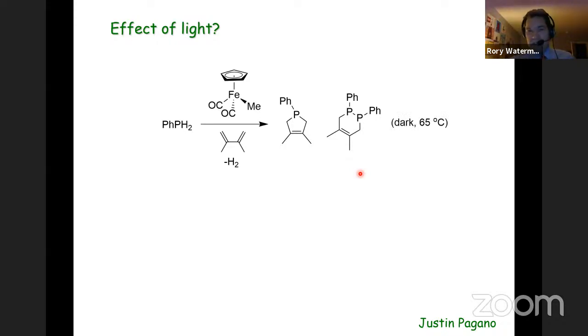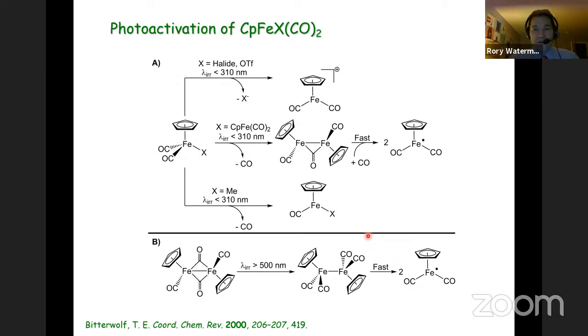It works in the dark, so it's clearly not photo dependent, and 65 degrees is the standard temperature for that particular transformation. We were curious though about whether photolysis would displace that thermal reactivity, and in fact it does not. So under ambient temperature with irradiation, FpMe does not do the same phosphinidene transfer that we were looking at a minute ago. However, there is very rich photochemistry associated with these CpFe(CO)2 fragments, and I show a summary of that borrowed from the late Thomas Bitterwolf's excellent review on the photochemistry of these systems. And really, a lot of that can be driven to the 17 electron Fp radical.